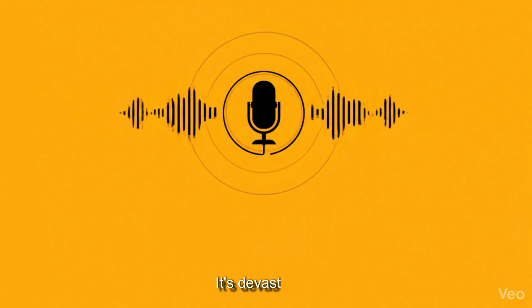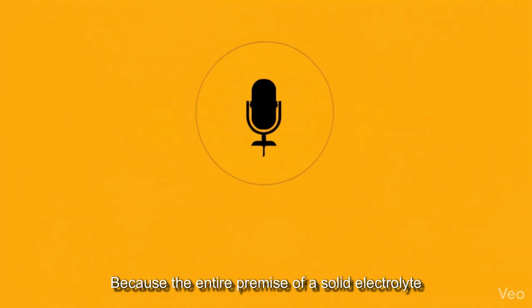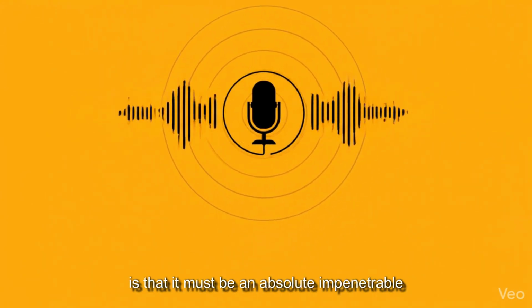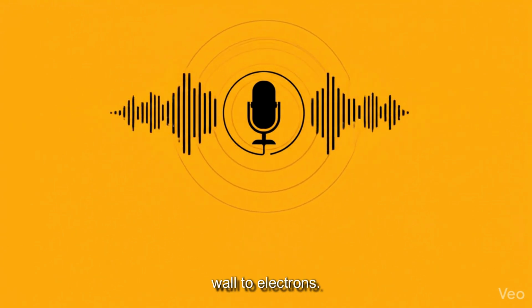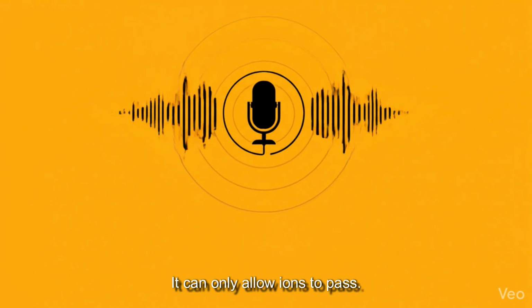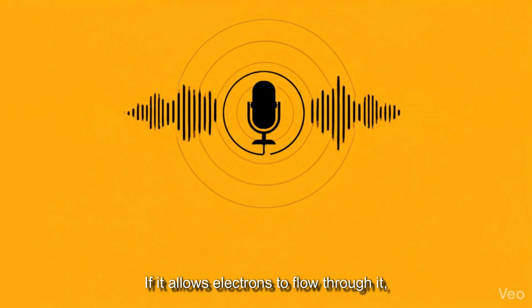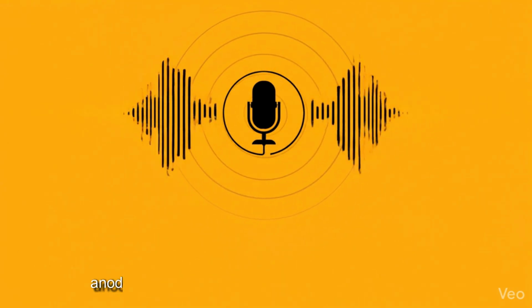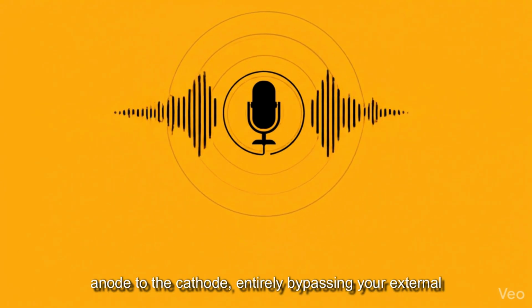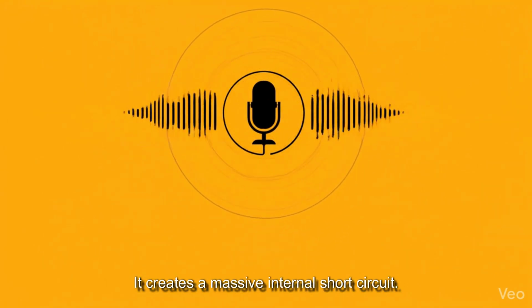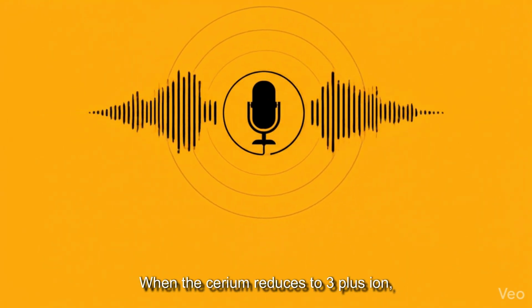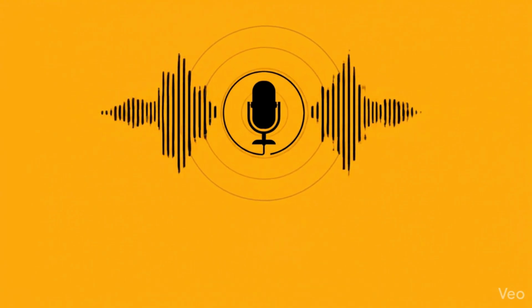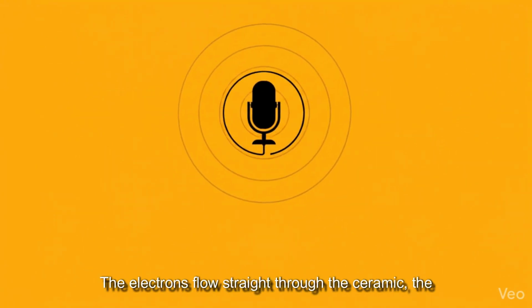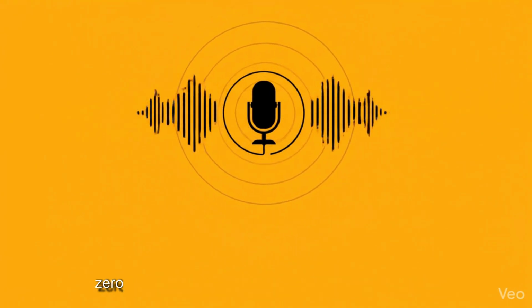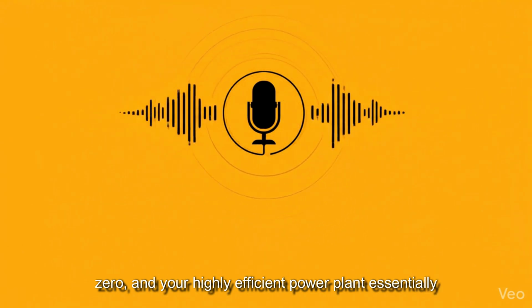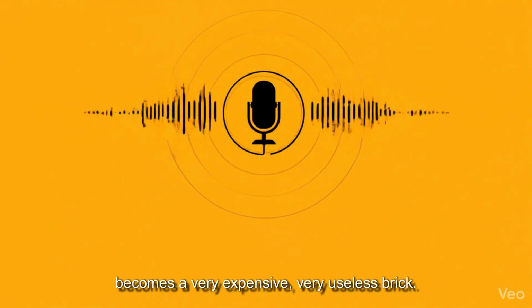Which sounds like a minor chemical curiosity until you realize what those freely moving electrons do to the function of the machine. It's devastating. Right, because the entire premise of a solid electrolyte is that it must be an absolute impenetrable wall to electrons. It can only allow ions to pass. If it allows electrons to flow through it, they just take the shortest path from the anode to the cathode, entirely bypassing your external wire. It creates a massive internal short circuit. Yeah. When the cerium reduces to 3+ ion, the material gains electronic conductivity. The electrons flow straight through the ceramic, the voltage collapses, the power output drops to near zero, and your highly efficient power plant essentially becomes a very expensive, very useless brick.